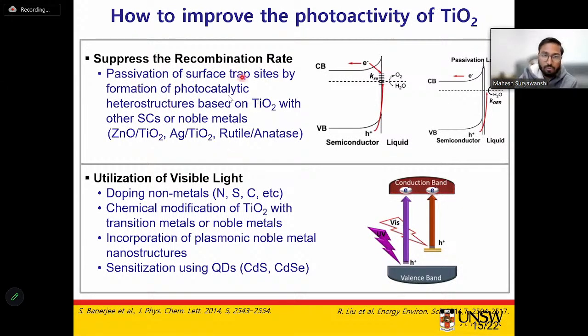So once you passivate those surface traps, probably this schematic might be clear to you to understand that concept. If we passivate those surface trap sites or surface defects, then we might get more and more generated electrons for the water splitting reaction to proceed. So how can we passivate this? By simply putting another metal oxide layer on top of TiO2, or simply putting silver on top of TiO2, which is a noble metal, also a plasmonic metal, or making heterostructures of the rutile TiO2 phase with the anatase phase. This is one way we can improve the performance of TiO2.